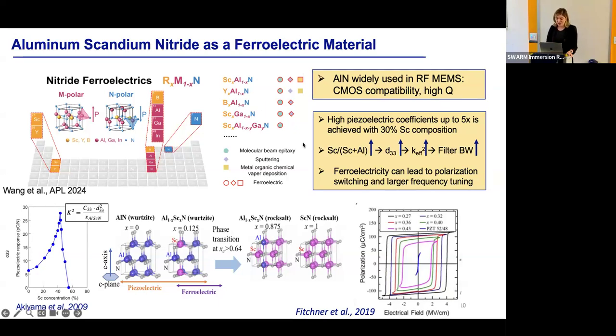Now, in recent years, scandium has been added to the aluminum nitride lattice. And people have observed that the piezoelectricity can actually increase by 5 times as you add more and more scandium into the aluminum nitride lattice. This was shown in 2009. And the reason for that is that the wurtzite crystalline structure of aluminum nitride starts changing, the c to a lattice constant proportion changes, and the piezoelectricity increases.